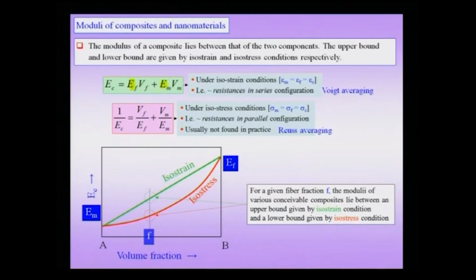In the case of isostrain conditions, that means the strain in the matrix is the same as the strain in the fiber, which is the strain in the composite. I get a formula that E c is equal to E f V f plus E m V m, where V f is the volume fraction of the fiber and V m is the volume fraction of the matrix, which is nothing but 1 minus the volume fraction of the fiber, assuming that there are only two phases in the material, with no porosity, etc. This resistance in series configuration gives me the modulus of the composite. This kind of an averaging is called Voigt averaging, and I can get the modulus of the composite.